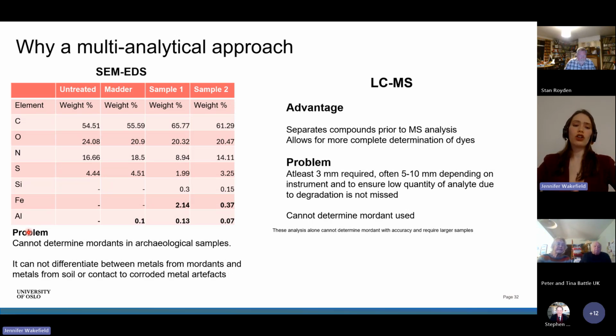The problem is with the archaeological material, because it's been buried, some metal ions from the soil could go into the woolen objects. Therefore, the presence of these metal ions needs to be taken with a pinch of salt. You have to consider, has it migrated from the soil? Could it be from nearby corroded artifacts as well? These two samples are close by. They're not from two completely different artifacts in two different areas of the site. So it's more likely it's from the mordanting, but you can't rule out whether there are other factors at play.